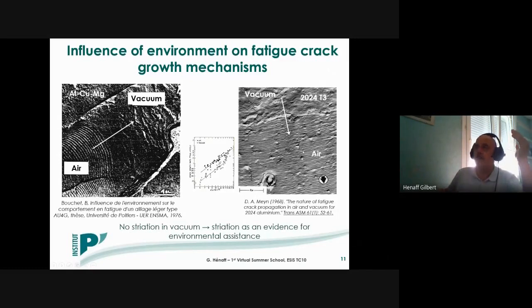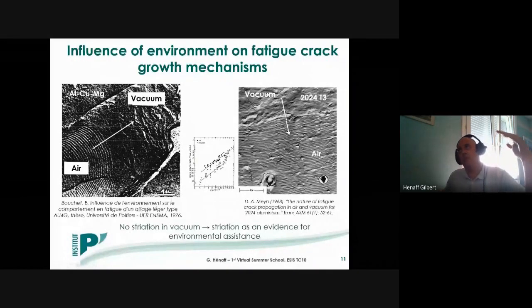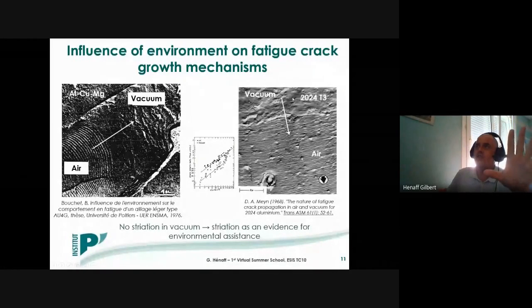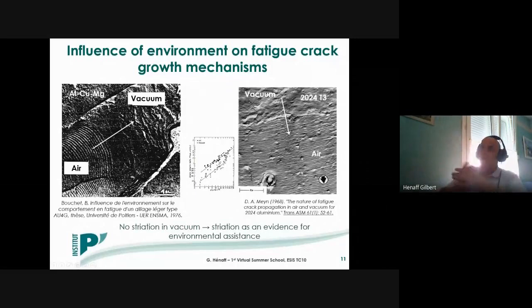And on the right-hand side, it's the same type of observations, except that in that case, propagation is first in vacuum and then switch to air. You can see that in that case, you have no striations in vacuum and the formation of striations when the environment is switched to ambient air. So what is really remarkable in that case is that the presence of these striations can be considered as an evidence of some environmental assistance.